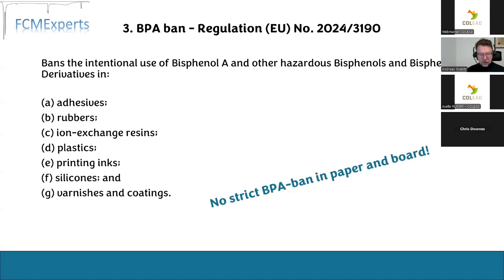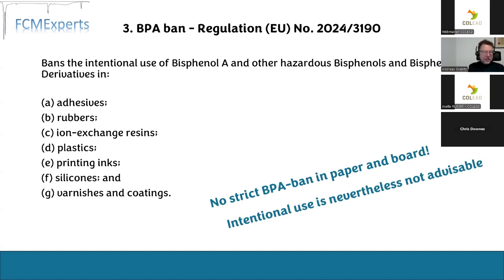But what you do not see here is that there is no strict BPA ban in paper and board. In certain countries there are limitations, mainly with regard to the release into the food, but this EU-wide ban of BPA is not applicable to paper and board. Nevertheless, the intentional use of BPA in paper and board is, of course, also not advisable, because we know these hormonal effects, these endocrine properties, are there. Therefore BPA should not be used by intention in paper and board. But it is rather clear, and we should understand, the restriction does not apply to paper and board, but only to plastics, printing inks, and so on.